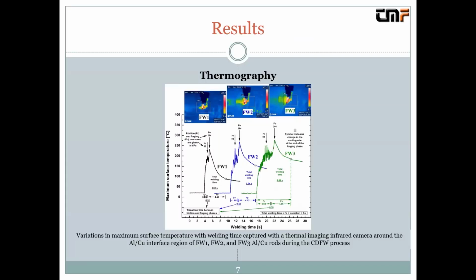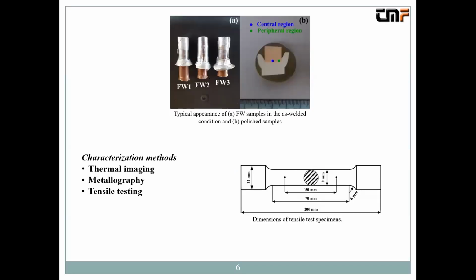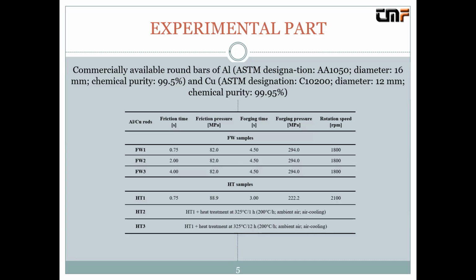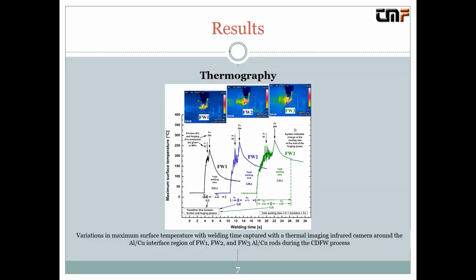So we will discuss the influence of parameters on the production. During the production, we used to follow the whole process by thermography. In that manner, we can see that. I'll just go back. As I said, we have 3 different samples, and the only parameter we varied was friction time. So with the increase of friction time, as we expected, we obtained higher temperatures in the welded joint.